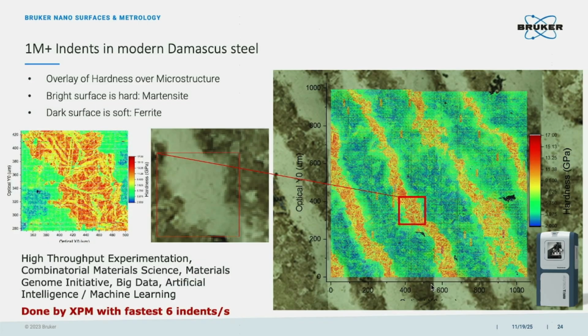So look at this. This is Damascus steel. There are 2 different phases we can see from the optical microscope. But we are using the fast indentation. We call it XPM. This is 6 indents per second. And we have performed the fast mapping many, many times and stitched all the mechanical mapping together. So you can see this is the image we are doing, from 1 millimeter by 1 millimeter. The mechanical properties align very well with the optical image.